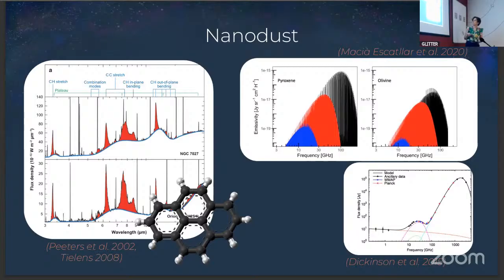Nanosilicates, though, have been proposed as a carrier for the anomalous microwave emission. That is the emission that is seen in CMB experiments, for example, where if you look on a large scale, you have thermal dust emission here, and on this side you have free-free emission. Rather than these connecting here, there seems to be some sort of excess which remains unexplained. That actually lines up quite nicely with the emission arising from, for instance, pyroxene nanosilicates or olivine nanosilicates at 20 Kelvin. Unfortunately, we do not have spectroscopic information on what this AME looks like, so we cannot match it up with the spectra that have been calculated here or any other proposed carrier. So it remains at this level a proposal.